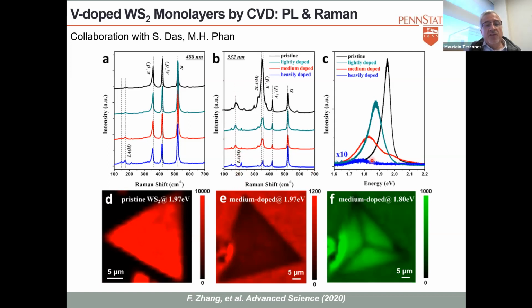So one thing that we see again, from the pristine, you have this direct band gap, as I explained. As you start doping it, you can see the shift in the direct band gap to lower energy. So you are reducing the band gap as you increase the concentration of vanadium. So this is the first thing we observed.